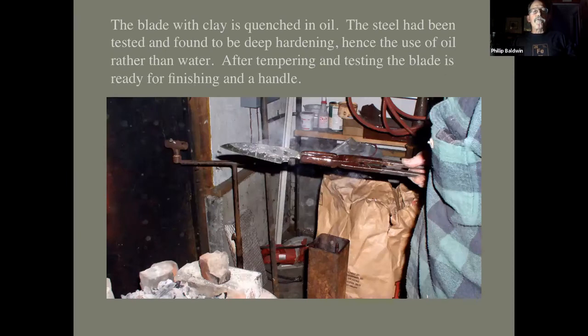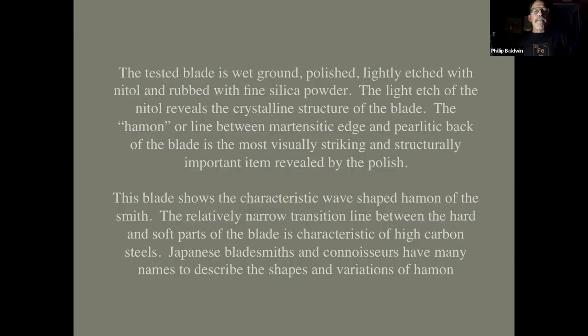That's after the oil quench. Then I temper it. I temper it by heating it in hot oil at 350 to 400 degrees for as long as it takes to get it to the hardness that I want. Next slide. And then I test the blade, put a rough edge on it and try to abuse it in a way that would be most likely for the intended purpose.